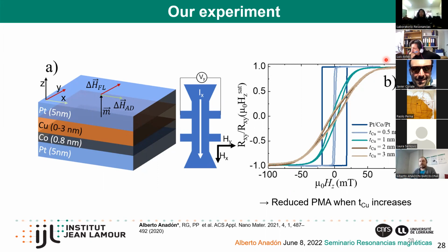Yeah, more that we see a loss of PMA in this curve. This is basically because the origin of the PMA in this system is the interfacial anisotropy from platinum cobalt. When you lose this interface, for thinner copper there can still be some interaction between the platinum and the cobalt. This is what you see here in the 0.5 nanometer. But when you have thicker than this, the effect of the platinum on top is lost very soon. Since you don't have the interaction between the cobalt and the platinum, you lose this interfacial anisotropy, and then your cobalt goes a bit more in plane. But as I said, this is not fully in plane. It's kind of tilted out of plane.